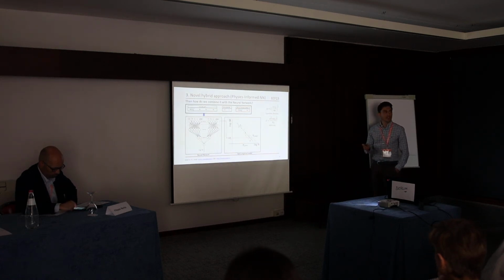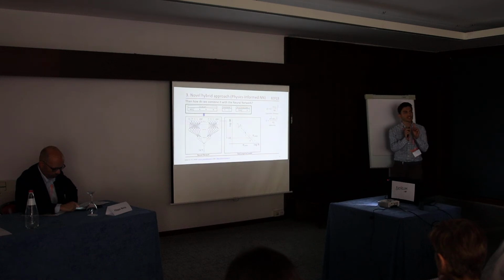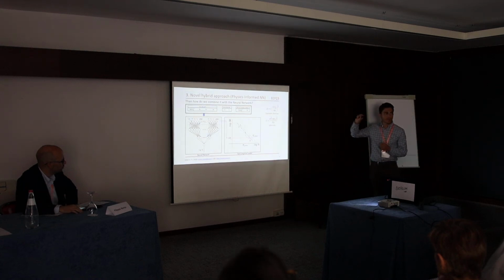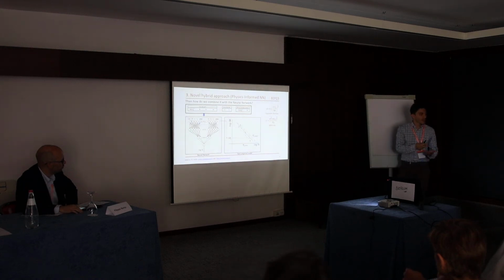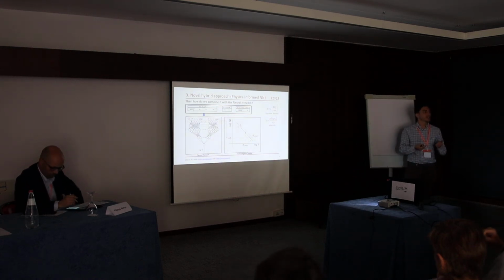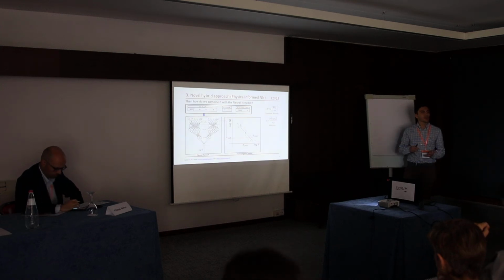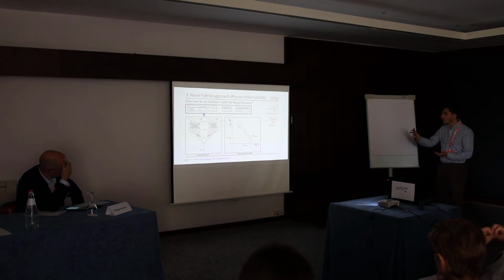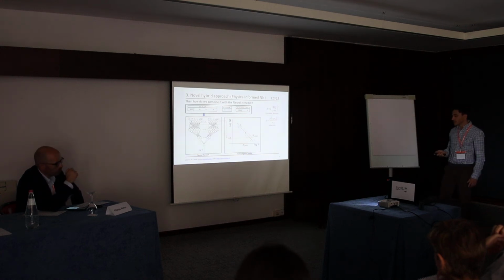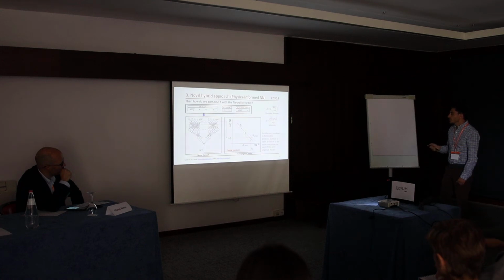Okay, we don't want an exact number. We don't want to match exactly the number of cycles. That's because this is a model based on defects, but we know that it's not only defects that play a role. There are residual stress, anisotropy, inhomogeneities related to microstructure, and so on. So the only constraint is that it must lie in this scatter band. So we force that, we add this to the loss, and then we run our model.